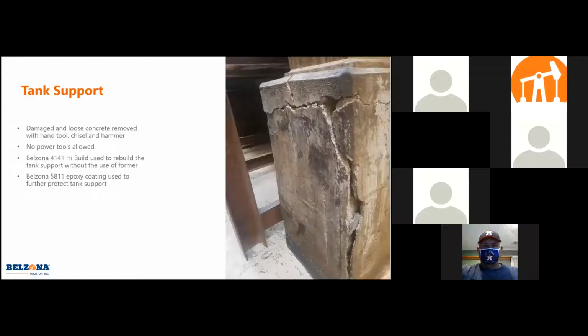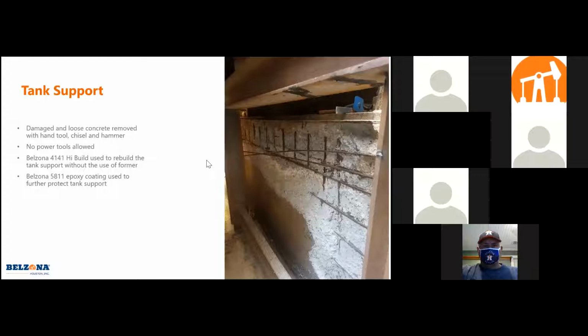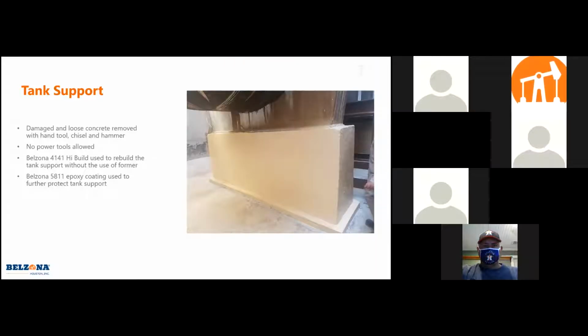And this is kind of another typical application: a tank pedestal, really cracked and corroded, cracked under stress here. So this is an application where they actually, no power tools were allowed. So they had to chip away all this with a chisel and hammer. And we ended up rebuilding it with our Belzona 4141 Hi-Build material because they didn't want to use a former here. So you can actually, without a former, get to this kind of consistency and end product. And then they applied a corrosion resistant epoxy over the top to give it a uniform finish. So a lot of concrete.